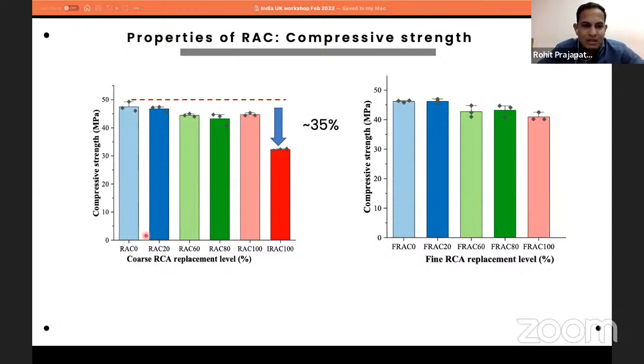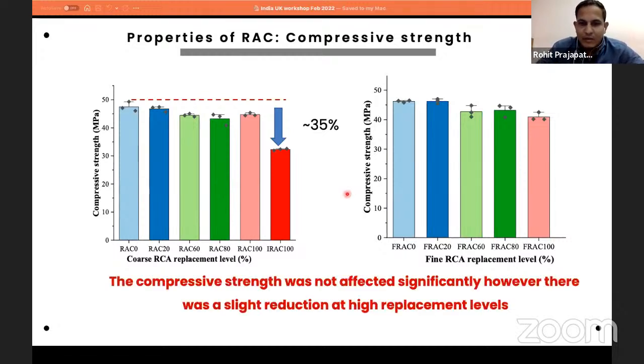So you can see that even if you replace 100% aggregates, the mechanical properties or the compressive strength has not reduced much. And here I have plotted one case where if you use untreated aggregates, it could go down up to 35%. Similarly, in fine aggregate replacement also, we did not find any significant drop. And we also have done other tests such as flexure test and complete stress strain curve. And then we could find that all replacement ratios, we could get the similar performance.